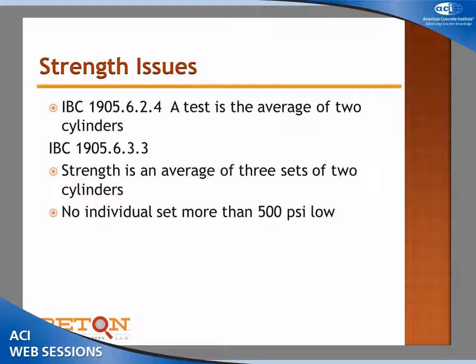So let's see how simple we are for testing. This is a pretty straightforward specification, but it's something that I often have to remind people. A test is the average of 2 cylinders, not the 1 cylinder you decided to break. And the strength is specified, over a performance basis, to be the 3 sets of 2 cylinders, not the cylinder you broke yesterday. No individual set more than 500 psi low.